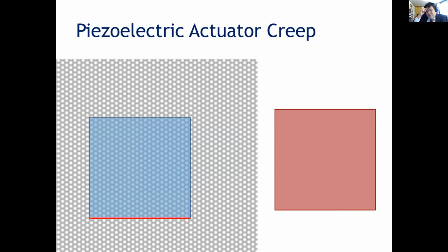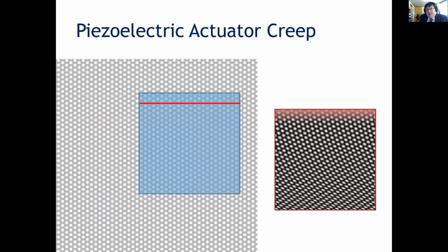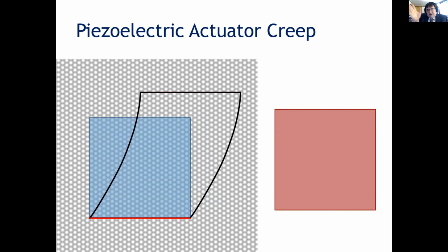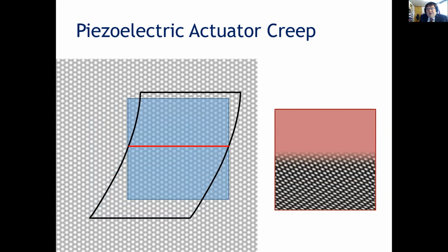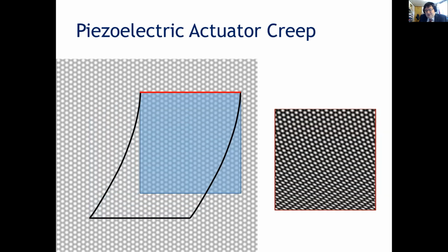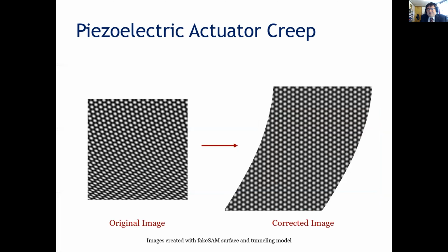But you also have piezoelectric actuator creep, which looks just like drift, except with time-dependent drift velocity. So it starts moving really fast and then it's moving really slow. And so you get an extremely complicated shape. But if you break it down into parts, it's not too bad. I trust you that you'll understand by the end of this talk how we go through it. So all we got to do is show the image in this shape, and it's undistorted.